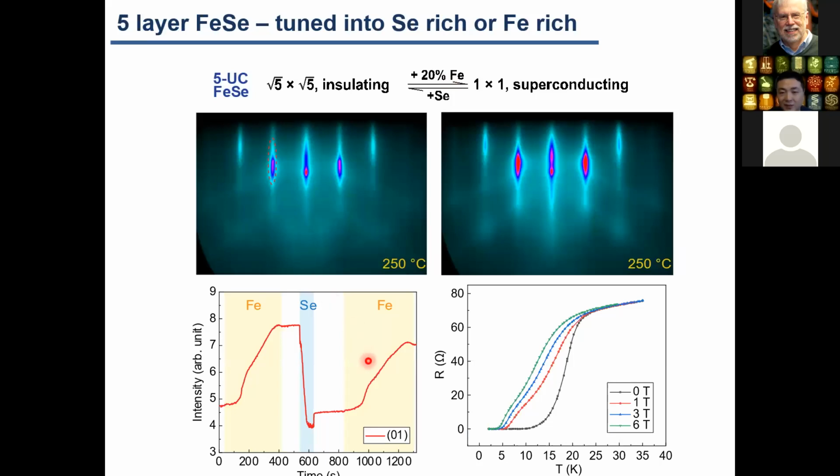and forth, more cycles. And after we add a certain amount of iron, we can recover the superconductivity in these multi-layers as well. So all this I'm showing you basically shows that our theory of the tuning, our method of tuning the stoichiometry, works very well for these materials.